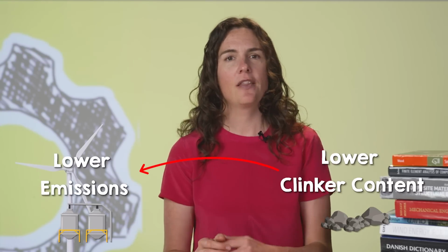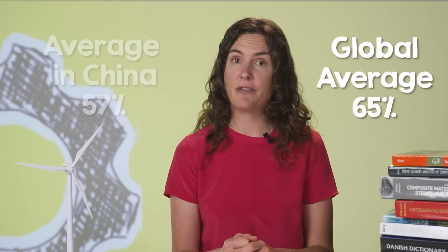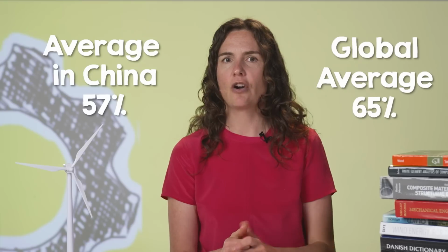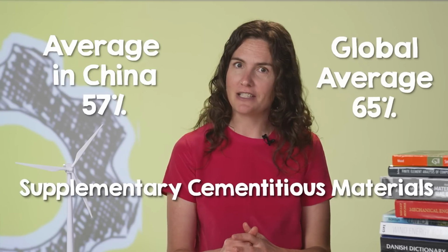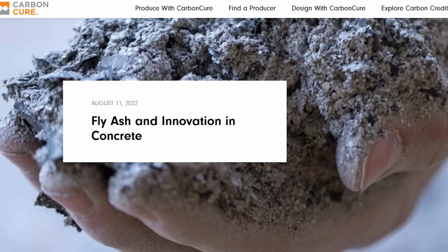Aside from replacing cement with lower emissions alternatives, another possibility is to lower the clinker content of cement. Because clinker is the emissions-intensive part of the process, a lower clinker content means lower emissions. The global average clinker content is about 65%, and the average in China is about 57%, with the difference coming from what's known as supplementary cementitious materials, mainly industrial byproducts like fly ash, blast furnace slag, and silica fume.